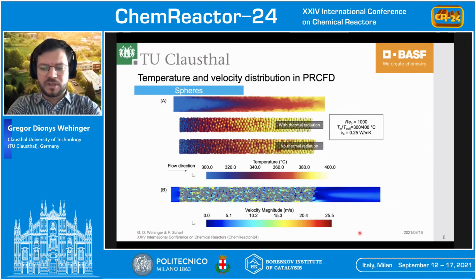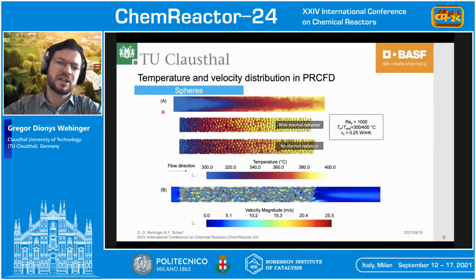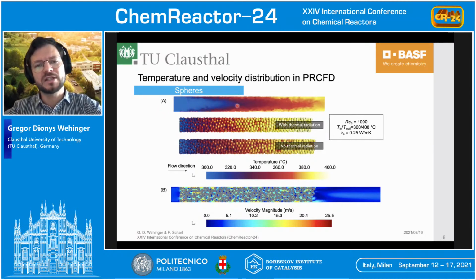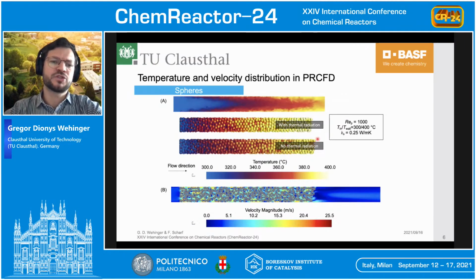Here I show you some qualitative results. As I said, flow is from left to right, and we see that the picture above is a cut through the bed, and we see that the fluid as well as solid is heated up irregularly. So sometimes we can identify certain particles, but then at the very end, we are very close to the wall temperature. Here we see the surface temperatures of the packed bed with and without thermal radiation for the same conditions. And as you might notice, we already see some hotter particles already at the beginning or in the first third of the particle packed bed. So that means this thermal radiation is an extra heat transfer mechanism.